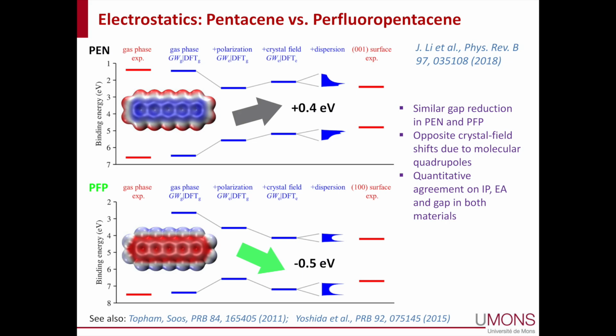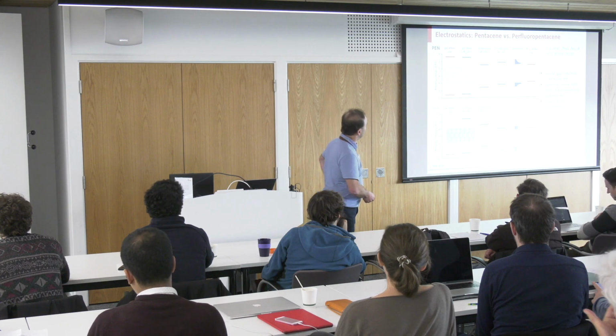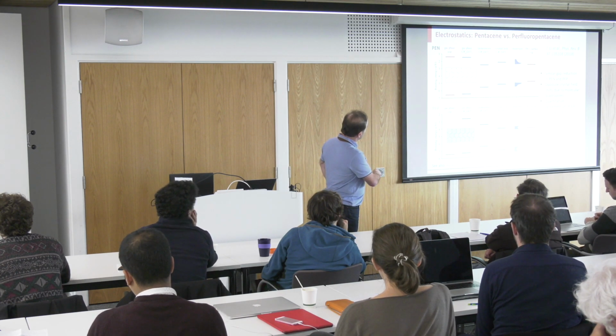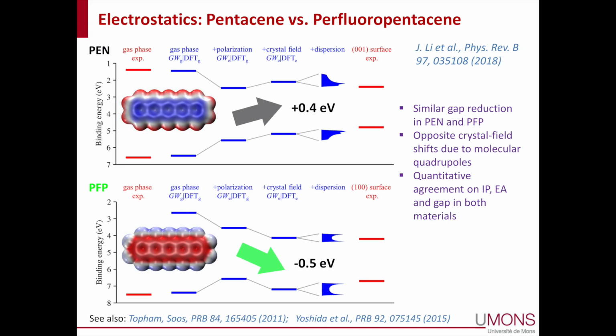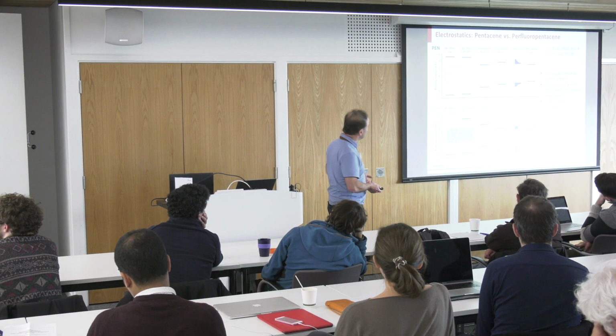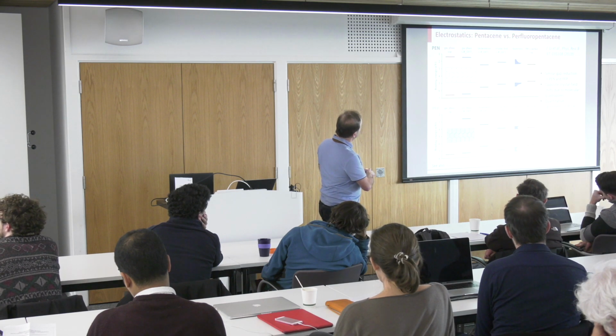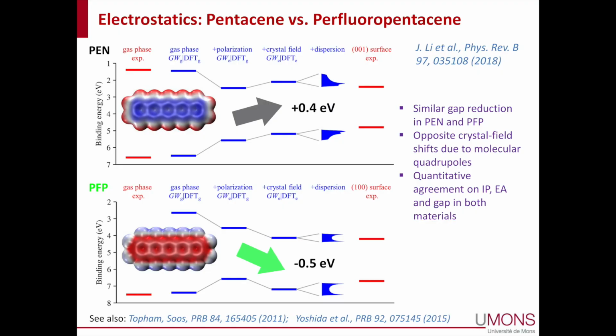And you can see the blue lines here are the theoretical simulations. Without going into the detail, you can use really highly accurate techniques nowadays to predict those numbers. There's another effect, which is just the interaction between the charge sitting on the molecule and the surrounding neutral molecules. So that's purely charge, multipole moment interactions, charge-quadrupole interactions mostly in those systems. And this will shift the energy levels, in this case, up for pentacene. But if you take perfluoropentacene, you see that the same charge-quadrupole interaction shifts the energy levels down. And this is the band dispersion, the quantum mechanical interaction between the molecules. And then you can compare to experiment, and it seems to work quite well.